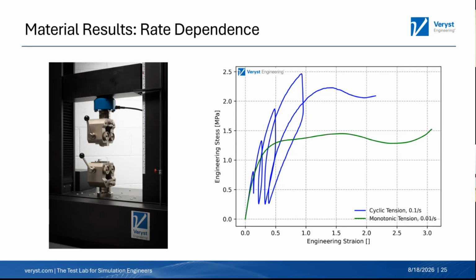So it takes 10 seconds to get to 10% strain. So it's taking 10 times as long, and you can see there that we're softer. We peak somewhere, we'll say at about 1.5 MPa. So that's a pretty large difference between those two. So we see this temperature dependence, and at the temperature that we're interested at, because we're near one of those transition temperatures that Scott was talking about, we're getting a very different material response when we look at the temperature.